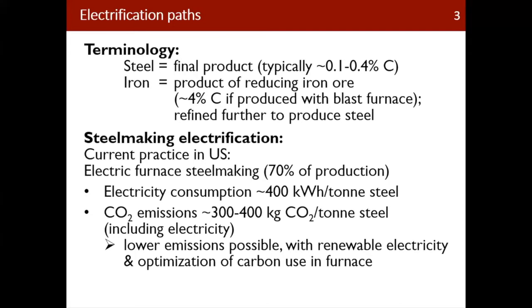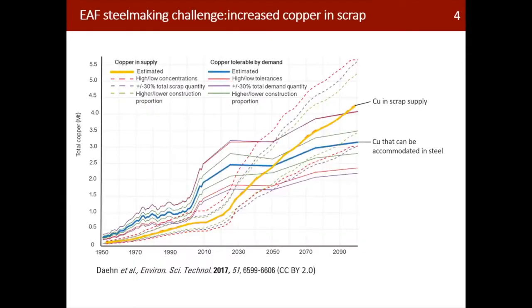The challenge to continuing down this path is the quality of scrap. So the main raw material for this kind of low carbon steelmaking is previously used steel that is then simply remelted, reformulated. There are certain elements that are more noble than iron and build up during this process. The worst pretty much of these is copper. And this chart shows various scenarios projected into the future as to how the amount of copper in the scrap supply is going to build up as we electrify our lives, and how the existing steel grades will no longer be able to absorb that much copper.